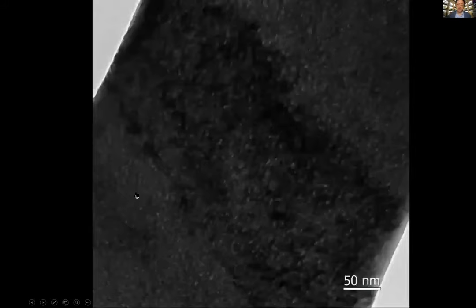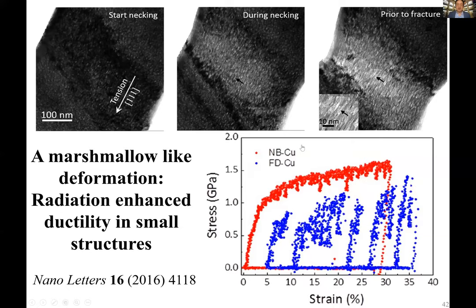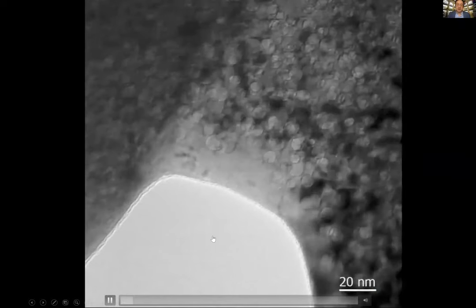When helium goes to grain boundaries, it creates a two-dimensional crack. That's very bad from a linear elastic fracture mechanics point of view, where the highest stress concentration is not a sphere or a needle, but a two-dimensional, penny-shaped crack. Also, all the grain boundaries are connected, so you have a natural percolating cracking system. If you don't have the cracks, helium is actually not bad for small-scale structures, on the order of a micron. So this is another proof.